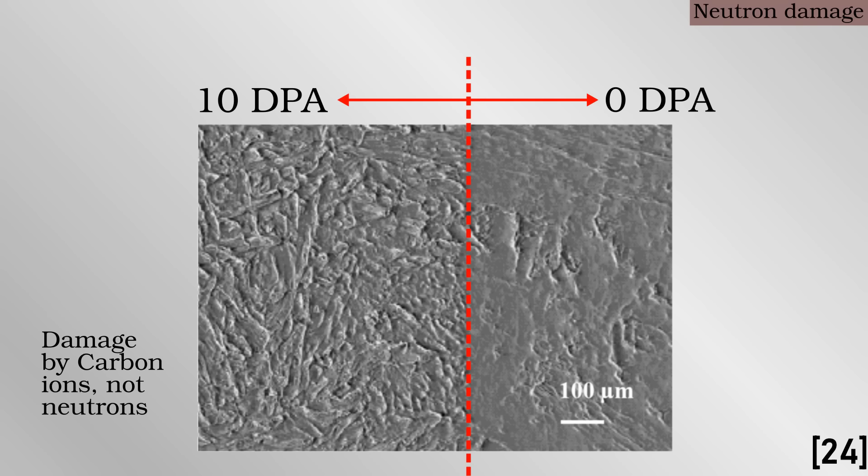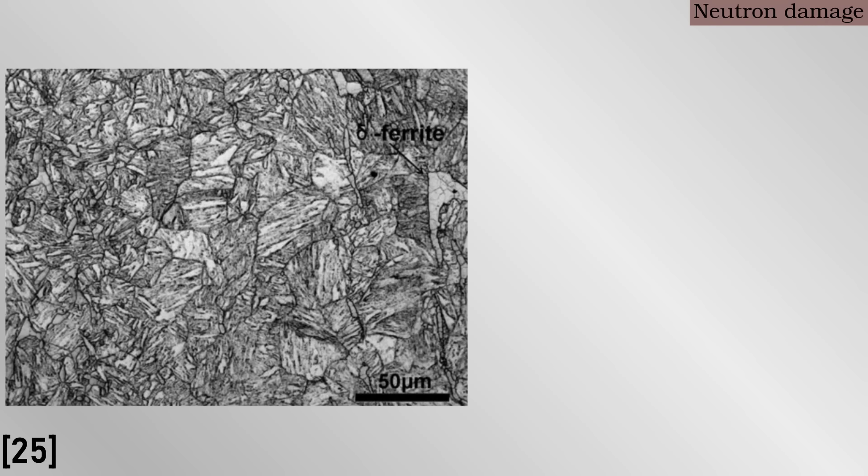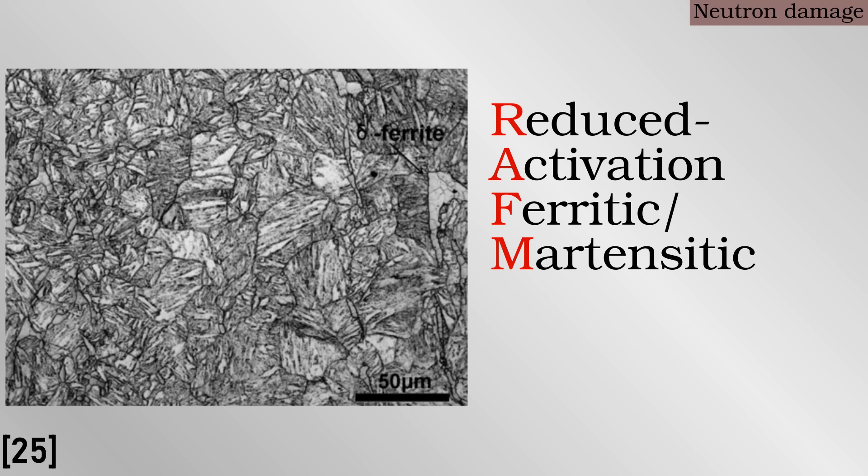The damage scales up with the number and energies of the neutrons. In many ways, this is uncharted territory for science. For the reasons I've mentioned, even fission plants do not reach these levels of neutrons. One particular concern is that microscopic gaps will open up in the material surface, trapping tritium among other substances. This would make the reactor components more radioactive on top of whatever activation is happening. The damage, particularly to the first wall, from neutrons and plasma in conjunction is likely to be severe in any fusion reactor. One family of materials being developed worldwide to deal with it are reduced activation ferritic martensitic steels, alloys of mostly iron, just under 10% chromium and up to a couple of percent other metals. The name informs us that this type of alloy consists of elements which do not easily become radioactive from neutron exposure and that they are rapidly cooled during manufacture in order to harden them. If you want to know how good they actually are at doing their job, then so would I. Quite a few tests have been done on small samples of these steels, but rarely if ever to the level of a fusion power plant and never on a fully structural component. The exact composition of these steels is still being optimized.